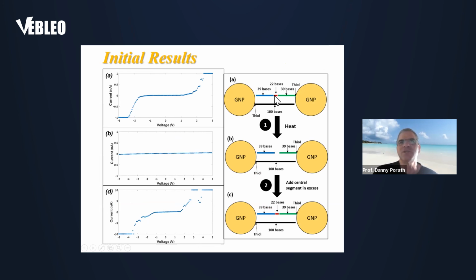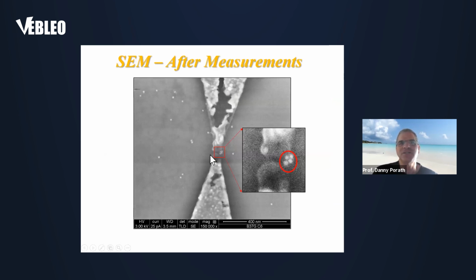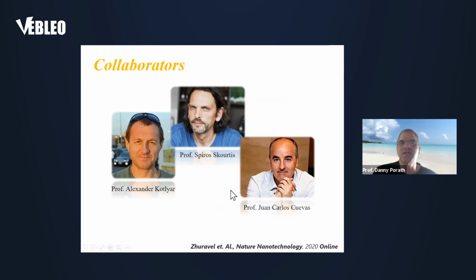That's the DNA with two 40 bases on the sides and a 20 bases segment in the middle, which has two nicks on both sides. And when we then raise the temperature and get rid of the middle segment, the current is suppressed. And when we expose it to the segment again, we get a recovery of the current. And here you can see the dimer trapped between the electrodes. There is another dimer, but it's connected only to one electrode.